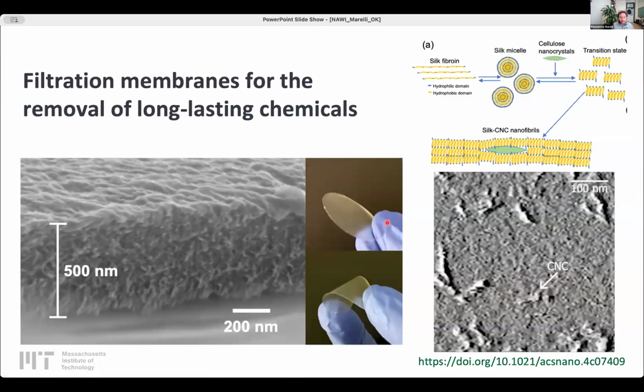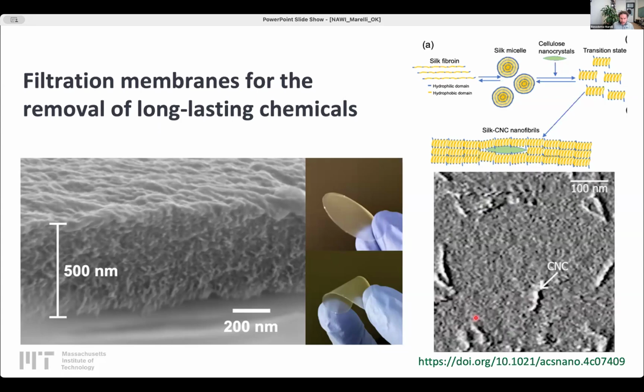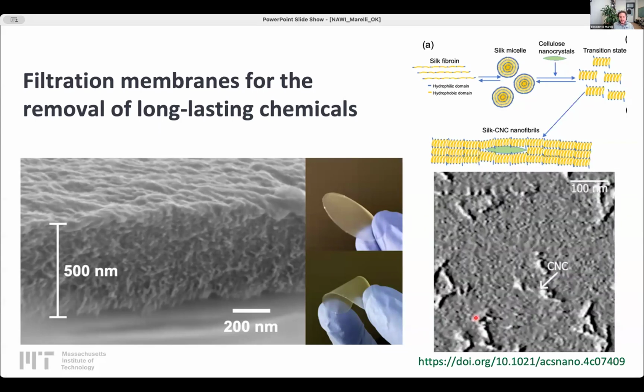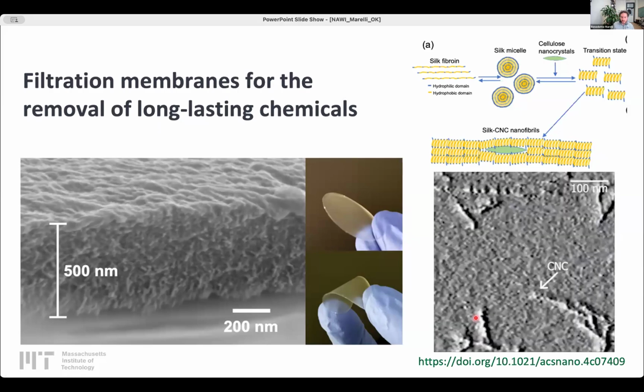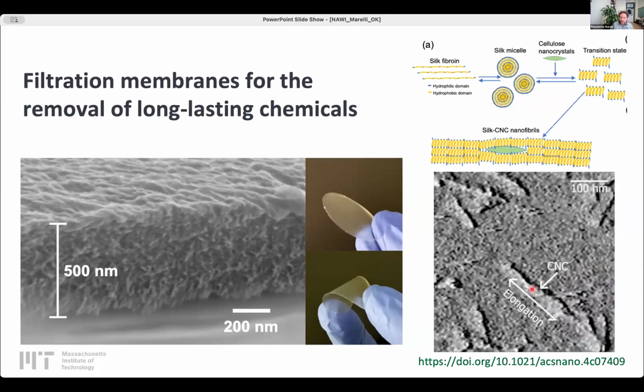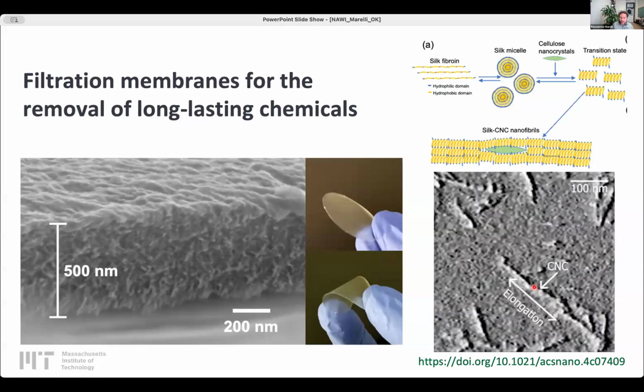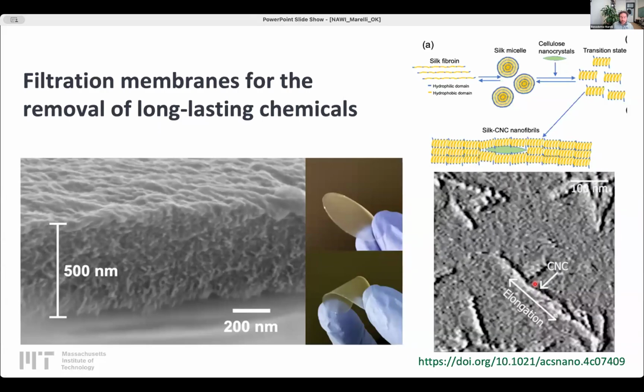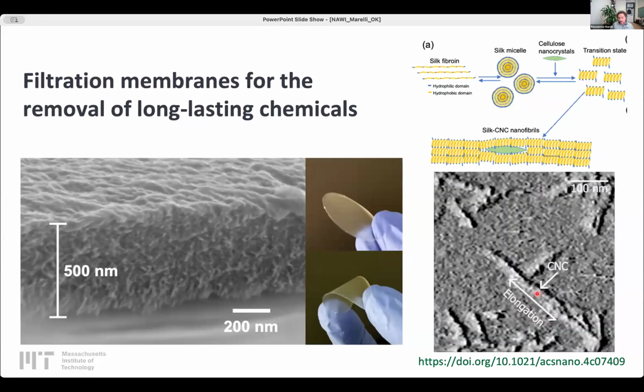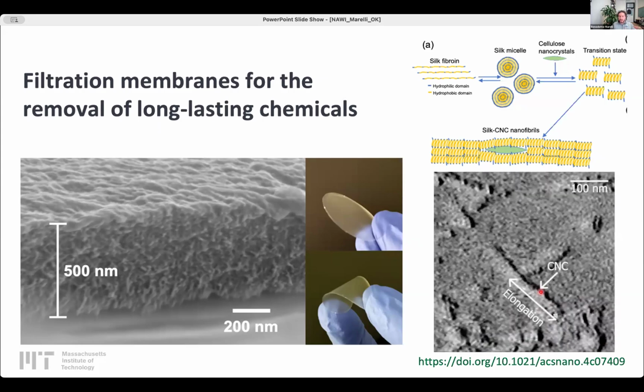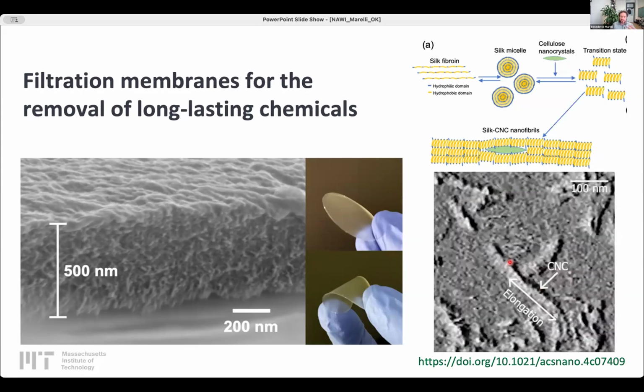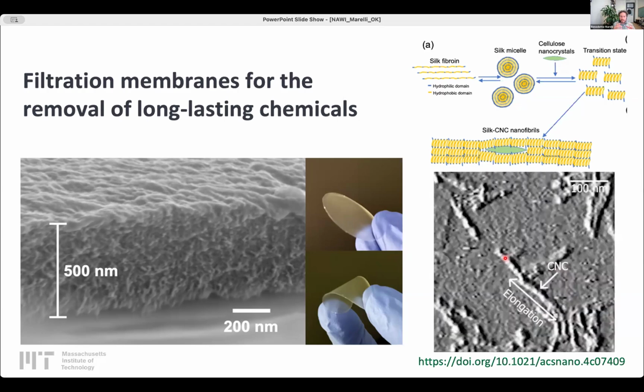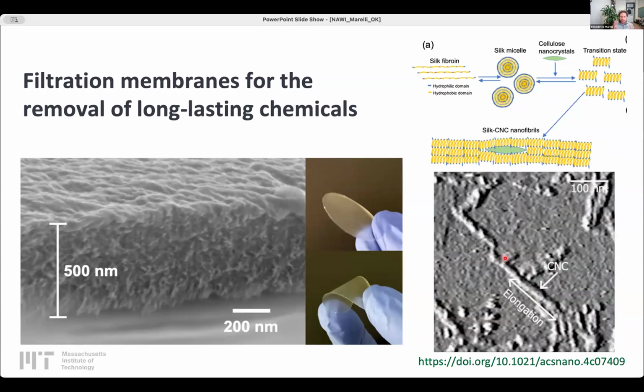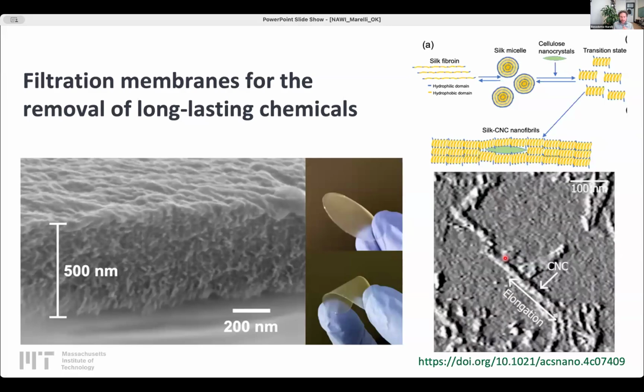And so what my lab developed is basically the application of this material to make membranes that can be used to extract PFAS from water. Particularly, we started from cellulose nanocrystals that we extracted from the pulp of wood. The cellulose nanocrystals in solution can template the growth of silk. Typically, silk, if it's self-assembled by water evaporation, forms a monolithic material.